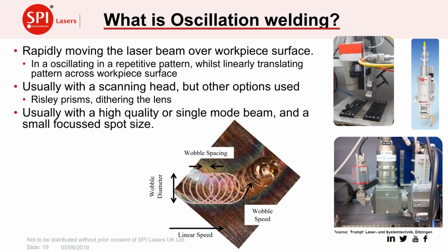We either do that by dithering the lens, or there's a set of devices called Risley prisms, which can be rotated to produce this pattern. Usually, in this case, we use a high quality or single mode beam with a small focus spot size. The little diagram is just showing an oscillation weld and the different parameters that might have been used there. We'll come back to those in a bit, but you can see there's a circular pattern overlaid there, which has produced the weld that we can see in the picture underneath it.